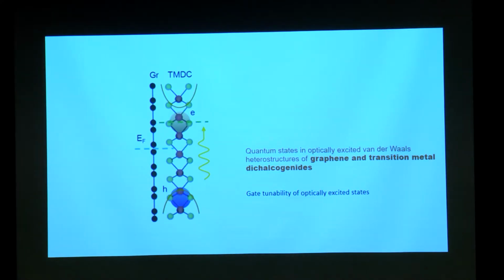The distance between the two is about half a nanometer, and we ask the question whether the transient optical state, which is essentially an electron here and the hole here, an indirect exciton, can exist in such structures. The reason behind asking this question is the extreme tunability of the structures with a metallic gate. I can apply an electric field across it, I can change the Fermi energy here, and hence if I can create a transient structure with the electron and hole in opposite layers, I can change its properties simply electrostatically, by using a gate from outside.